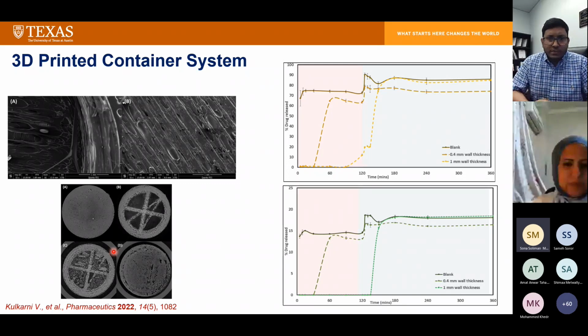And of course, we did the SEM imaging as well as micro CT imaging to see whether there was any leakage or anything. And we found that our developed chamber system or container system was quite consistent in terms of the printing, I think the composition or the morphology of the container system that we have developed.